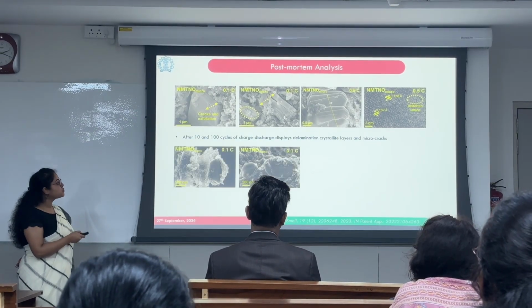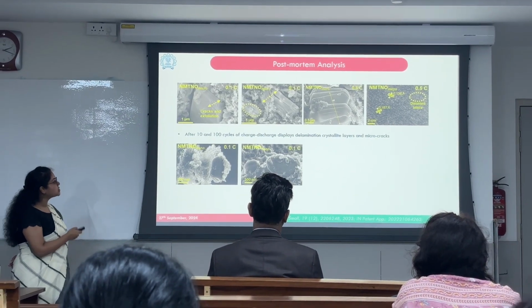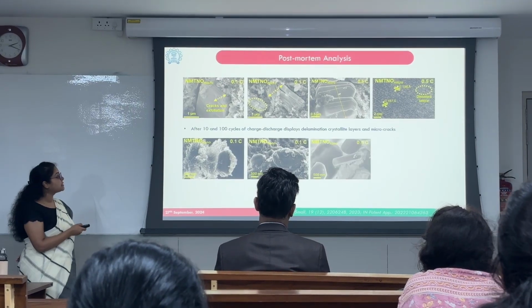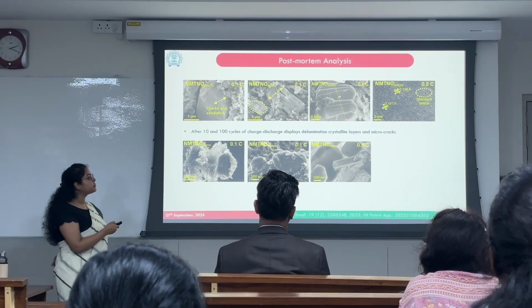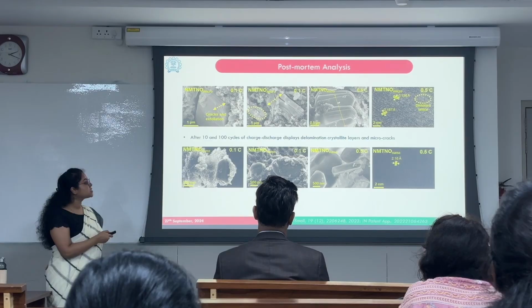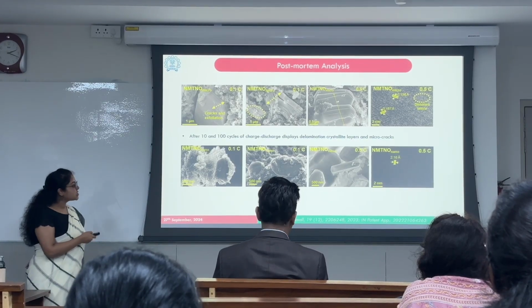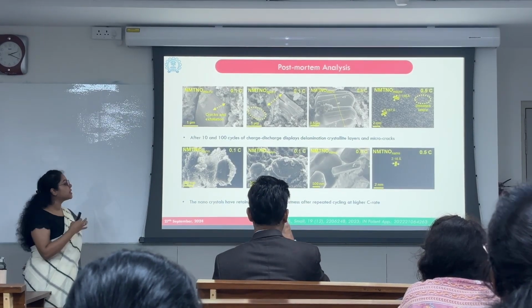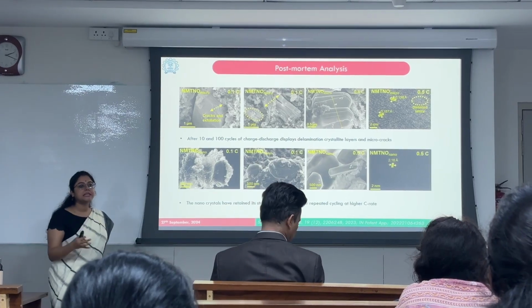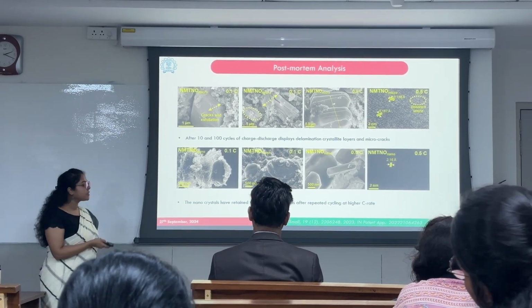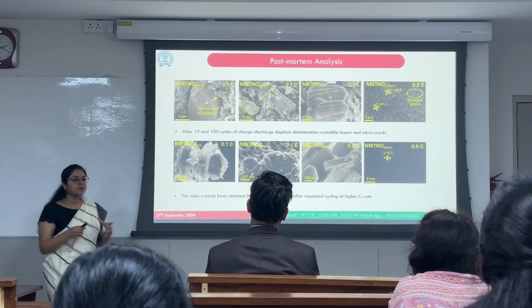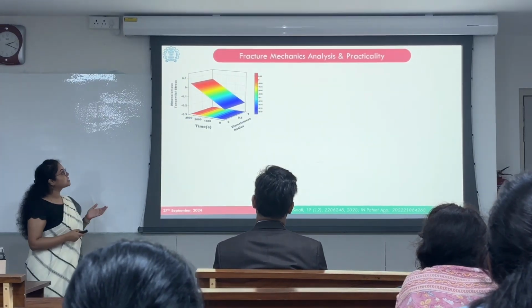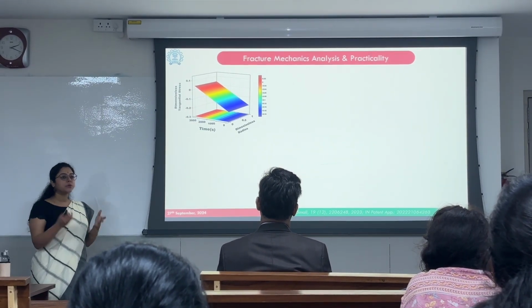However, in contrast to that, we do not observe exfoliation in the NMTNO nanoparticles even at a higher C rate of 0.5 C, and also through the high-resolution TEM, which suggests that the NMTNO nano was much more robust and retained the structure after prolonged cycling.